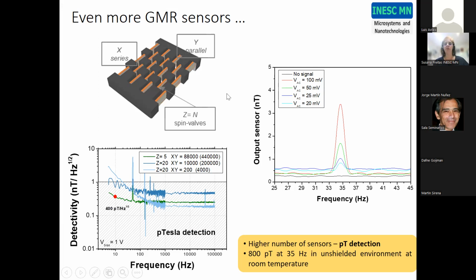If we have a large number, everything can be simulated. So these results could be simulated before the experiment is done. And the idea here is to measure, and we could measure picotesla, so 800 picotesla at low frequencies in a randomly noisy environment. So it's not a shielded room, it's just a noisy environment where the sensor is there in the middle of all this noise at room temperature. So this means that if we want to decrease the noise and to increase the signal to noise ratio, there are always strategies that require your imagination and the capability to build them in the lab.